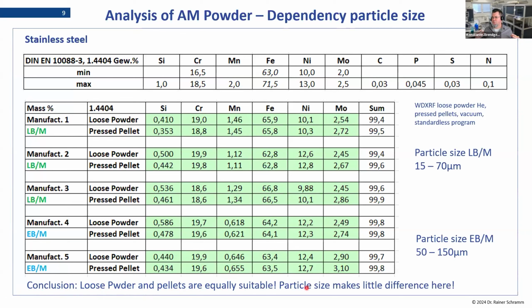So we can deduct from this that the particle size between the different powders for the different techniques doesn't matter that much, and also the advantage of doing a pressed pellet, which you usually see in the accuracy of results, is not really present here. So both are suitable depending on the time and equipment you have.